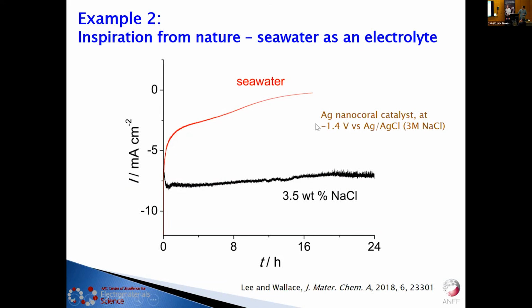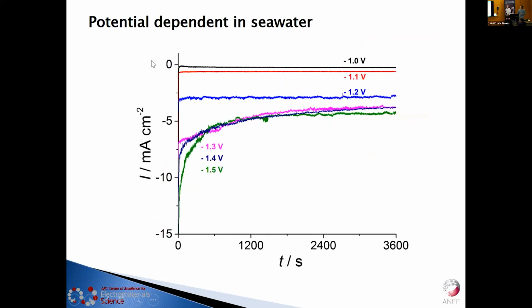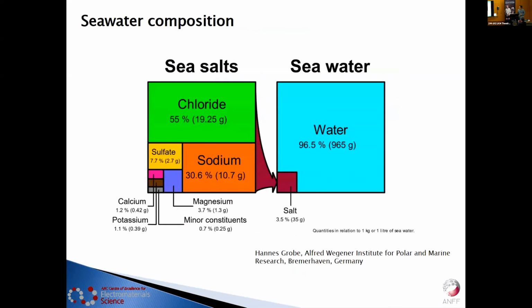You can see here, if you use seawater from Wollongong, not Wollongong Beach, the current drops down. So what is the reason for that? It shows a potential dependence. If we use a low potential, not really a negative cathodic potential, it doesn't make a huge difference. But when you increase the potential, the effect becomes more obvious. So we have to look at the seawater composition here.